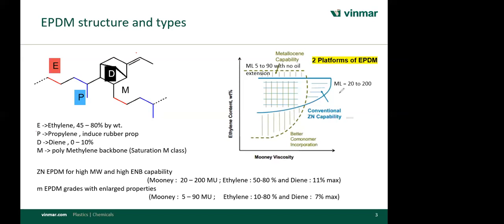In metallocene, we get the added advantage to reduce the ethylene content to 10%. So very low ethylene, low Mooney grades you can make out of the metallocene catalyst system. And in metallocene, we can make a maximum diene of 7%. So if any customer is using a grade for the sponge category or some fast curing grades, they are using some 10% or 11% EPDM diene content. If the supplier is metallocene, then 7% maximum you can get, but these are capable of fulfilling those properties. That's how the whole system has been designed.